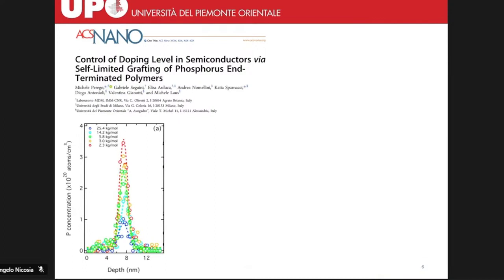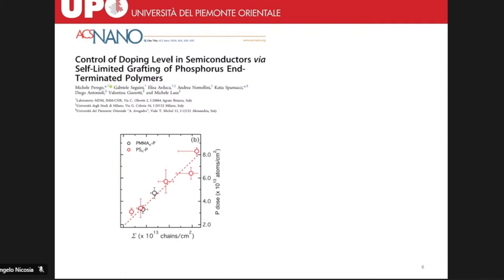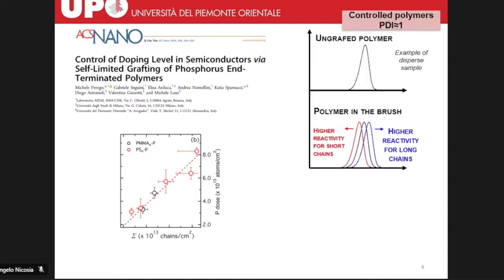So from the ToF-SIMS results, we observed that decreasing the molecular weight of the polymer results in an increase of phosphorus concentration. If we integrate all these profiles, we will find that the phosphorus does increase. And if we plot it as a function of the grafting density, we can see that it's a linear relation. But in this case, we are using controlled polymers. And recent studies in our group let us know that sometimes the molecular weight of the polymer before the grafting reaction and the molecular weight of the polymer that is forming the brush is not the same.